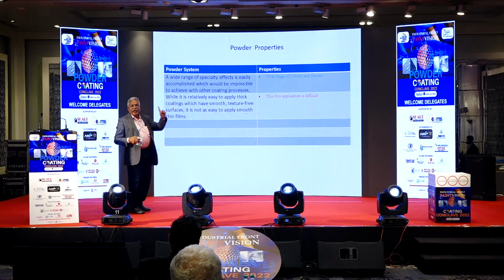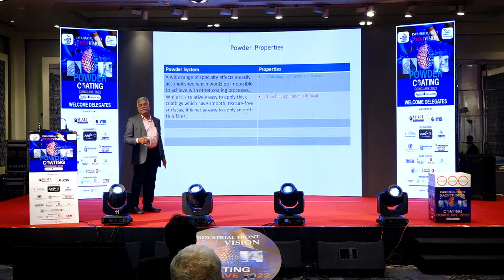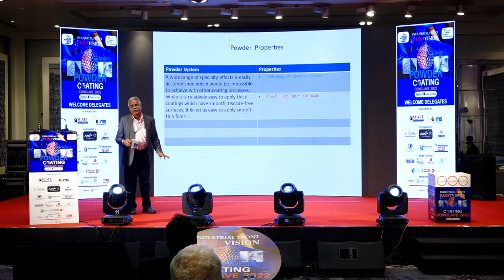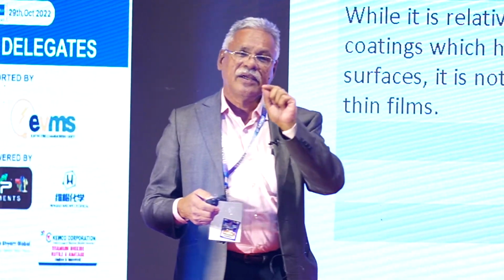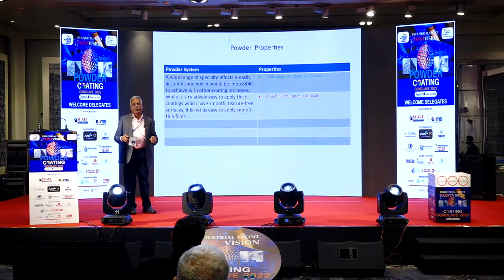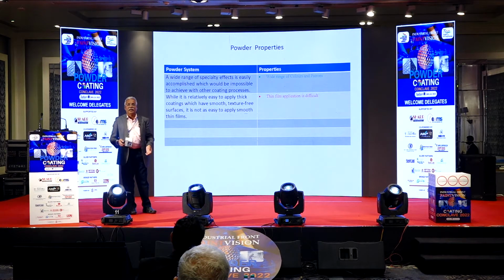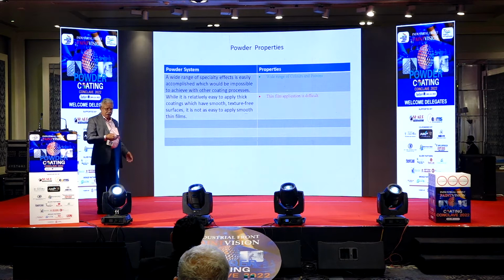The only difficult thing is thin film application. With powder coating you cannot go below 60 or 70 microns. Otherwise you will have bittiness, craters, or more waviness. So it is difficult at present. Maybe very shortly you will get suitable resins for thin coating also.